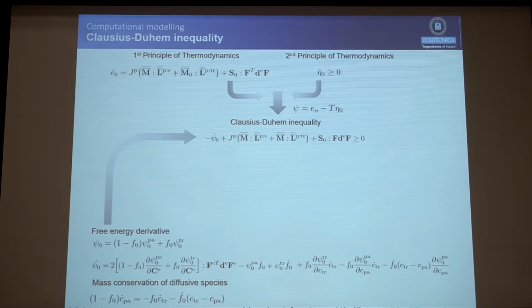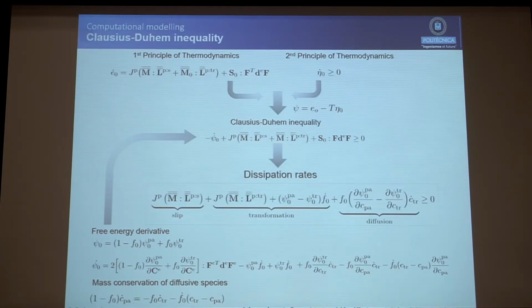We combine this together with this function into this Clausius-Duhem inequality, and after deleting some of the terms, we get to this dissipation rate equation, where we can see here the dissipation rate of slip, the dissipation rate of the transformation, and the dissipation rate of diffusion. We will forget now the diffusion part because this will lead directly to Fick's law basically, but by looking at these two terms, we can get the driving force for these two mechanisms.